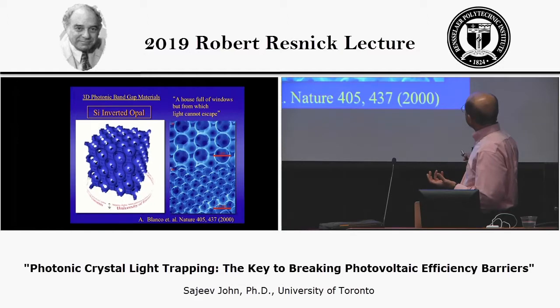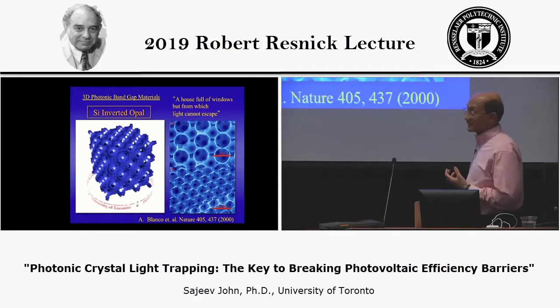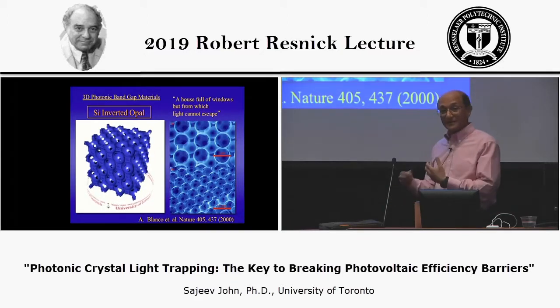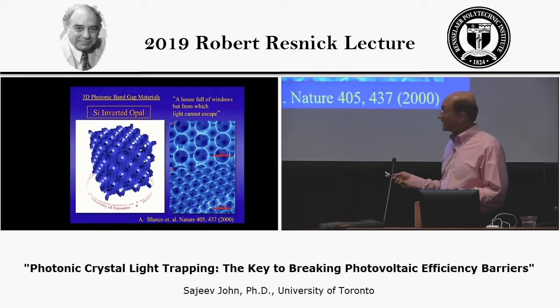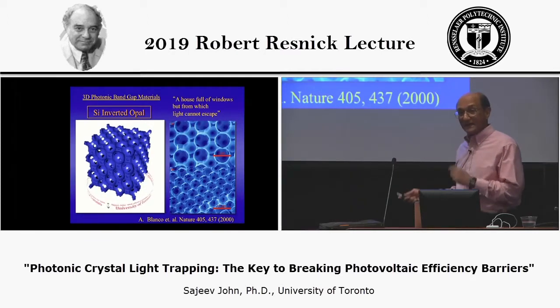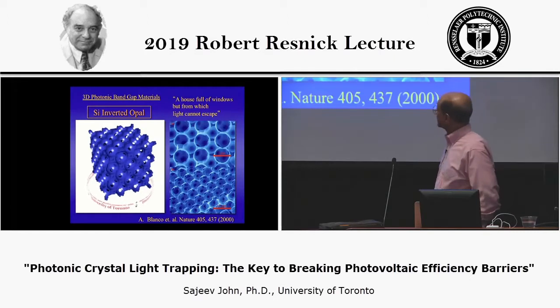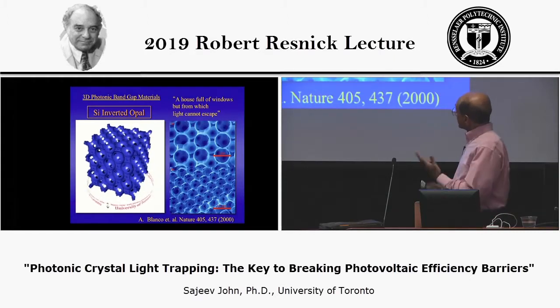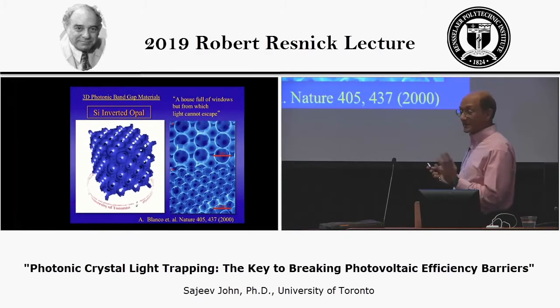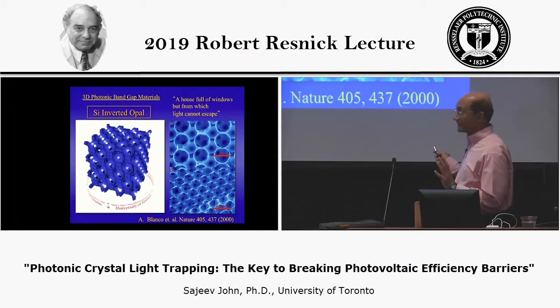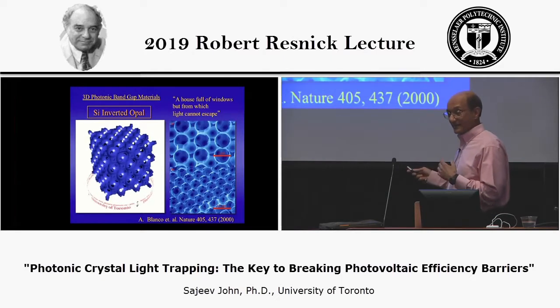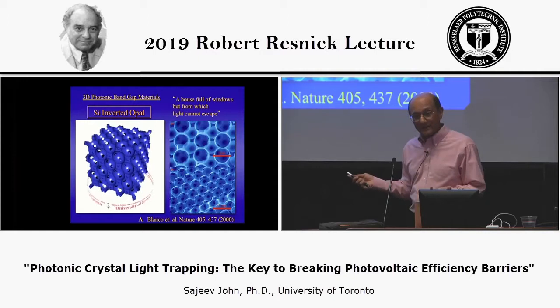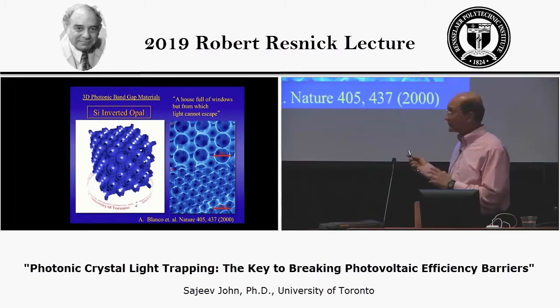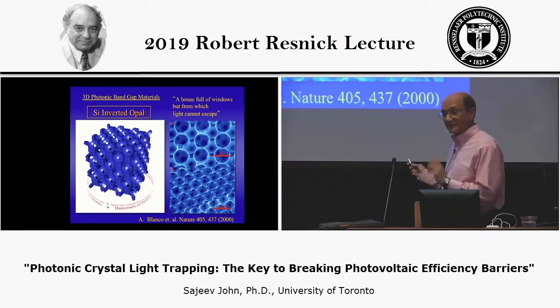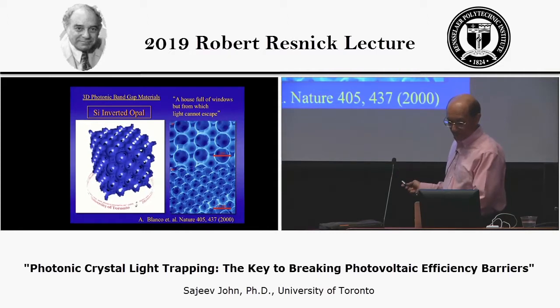The diameter of these spheres is 850 nanometers. This has a complete band gap, an absence of electromagnetic modes over a band near the 1.5 micron wavelength. So this is a photonic band gap material. It wouldn't make a very good solar cell because it has a lot of surface associated with it, and carriers can recombine at its surfaces, so we need to have something a little bit more appropriate to the application in mind for photovoltaics.